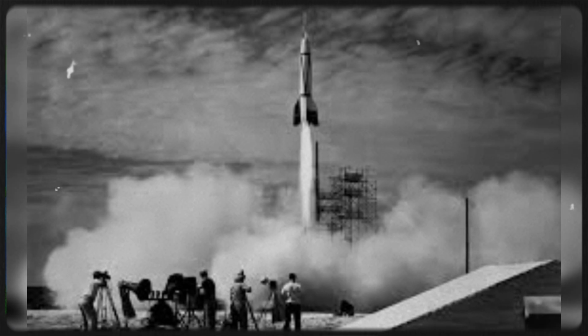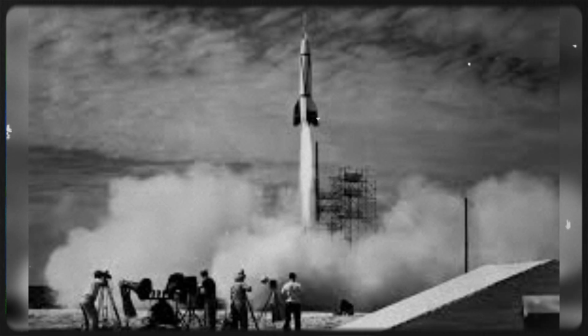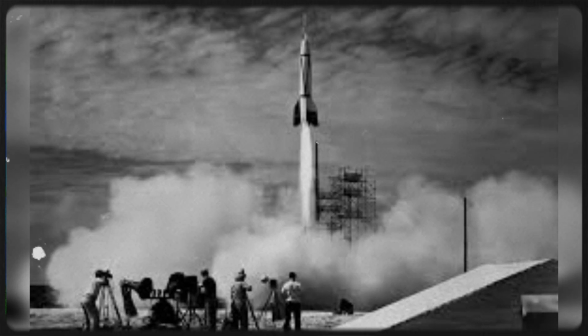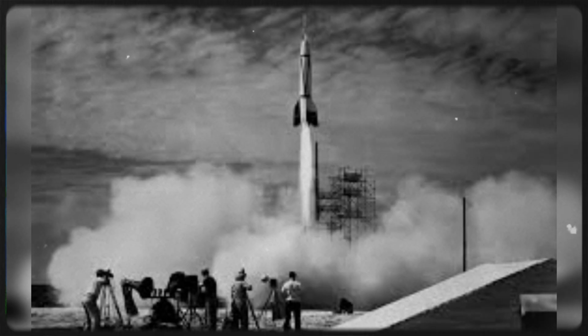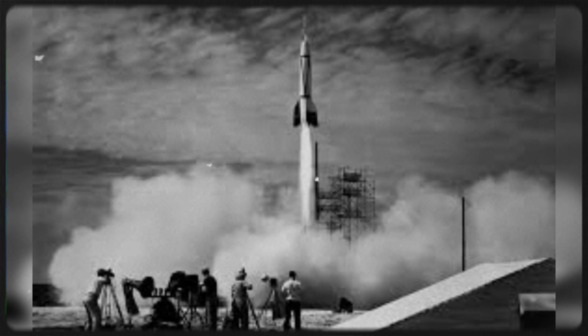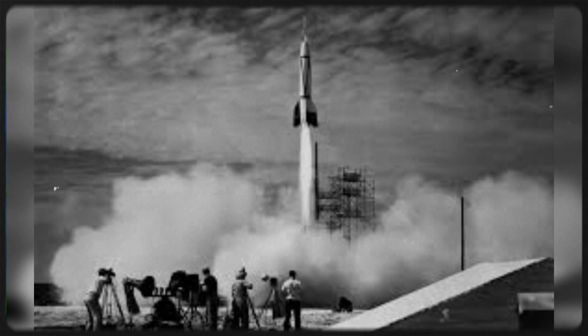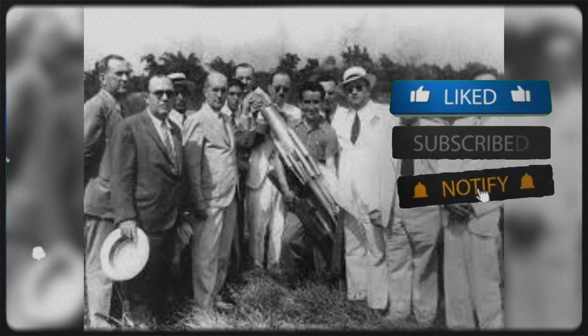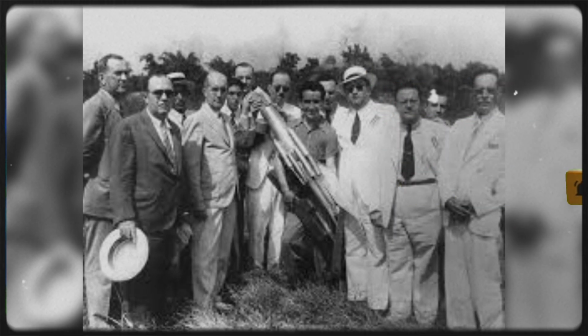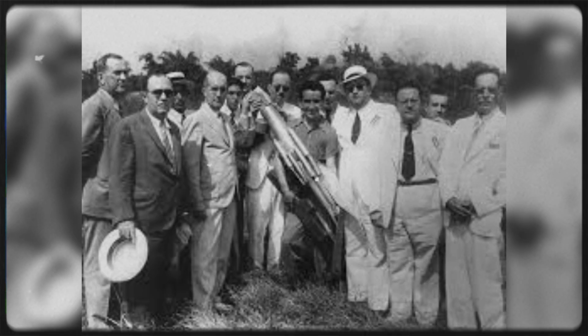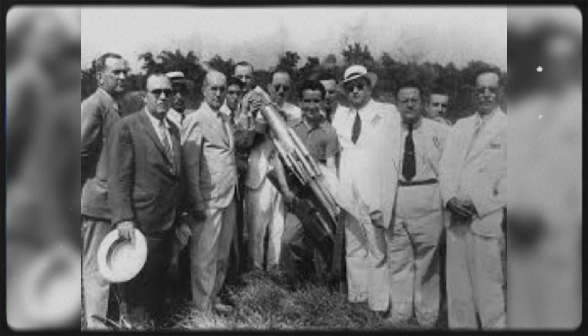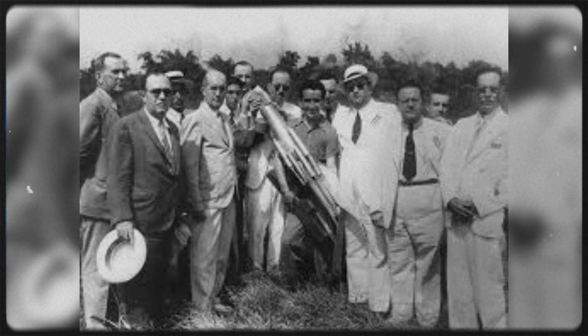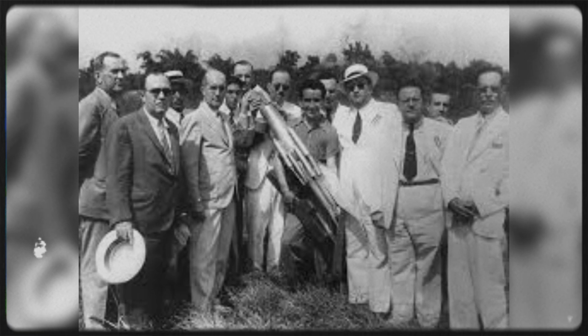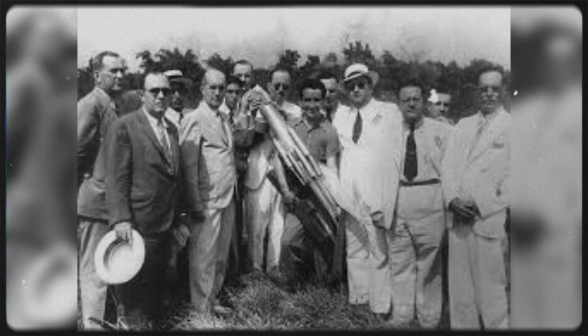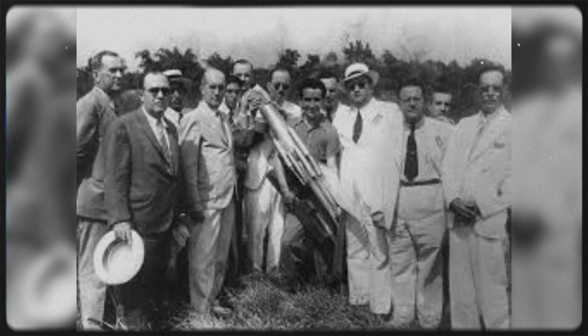By end of day, redesign had 47 modifications based on German recommendations. Lubbock compiled changes, ran new performance calculations. With modifications, predicted propellant flow, 91 kilograms per second instead of 85. Predicted operating life, 95 seconds instead of estimated 70. Predicted reliability, 94% instead of hoped for 85%. Timeline to functional hardware, 18 months instead of 30. Cost savings, approximately 140,000 pounds. The Germans were worth every pound of their salaries and the moral compromise of employing them.